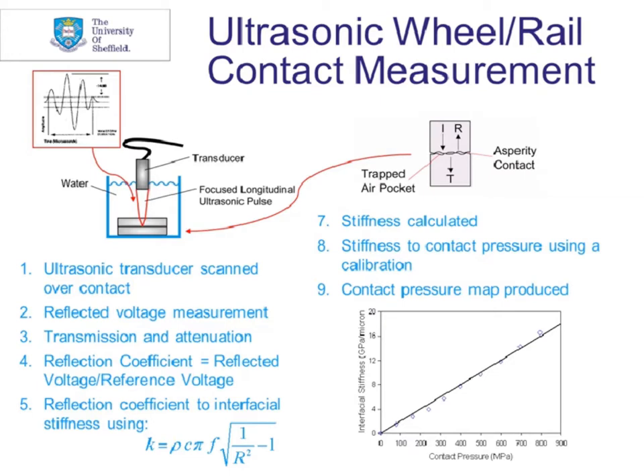And this gives you a reflection coefficient, and this reflection coefficient can be related to the contact pressure in a contact via the interfacial stiffness using the equation shown on this slide. So when you're measuring an actual interface, you can scan, get your map of reflection coefficients, and through a calibration taken separately, you can produce a contact pressure map, which is really useful.